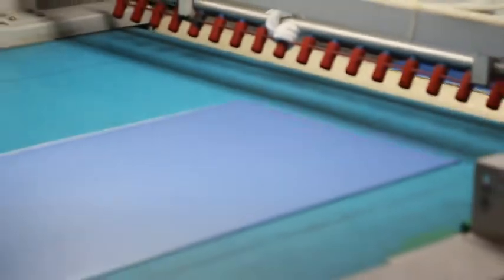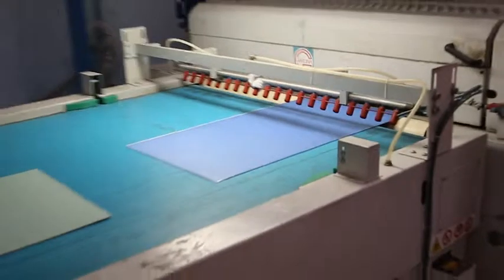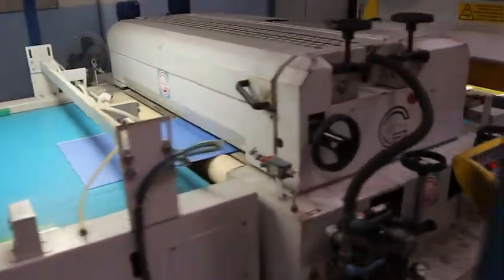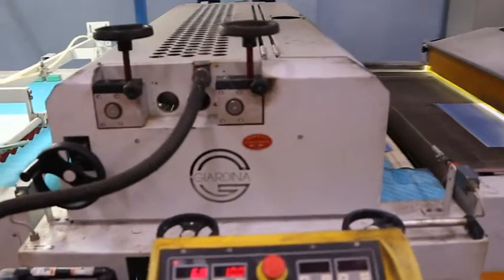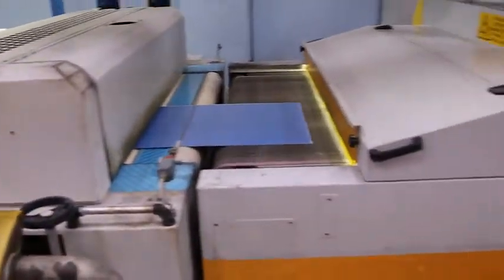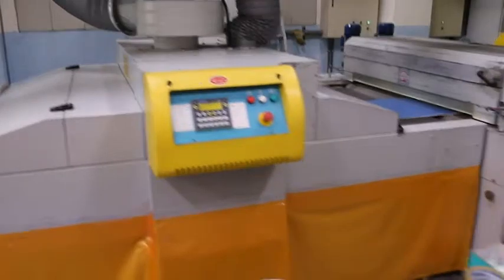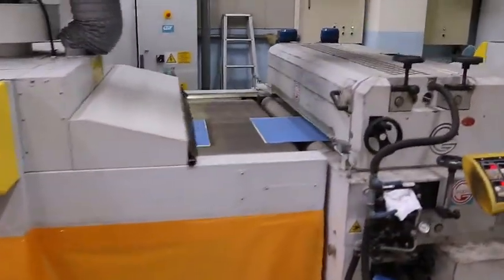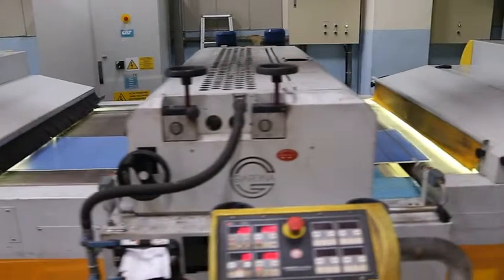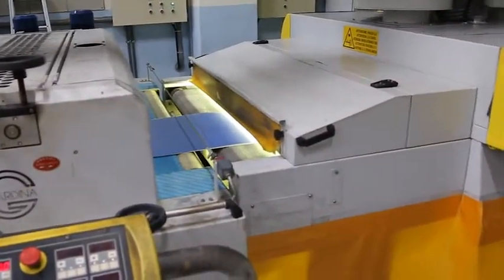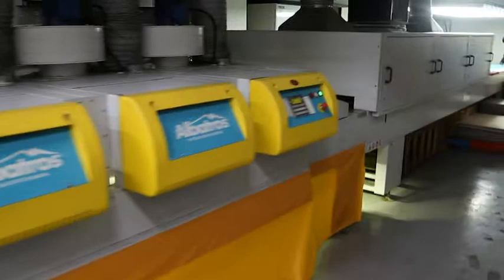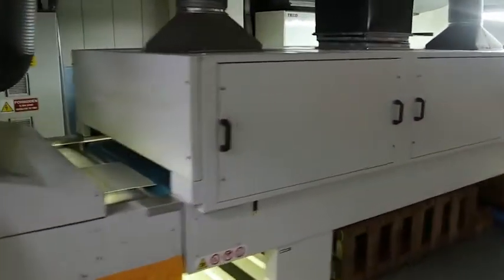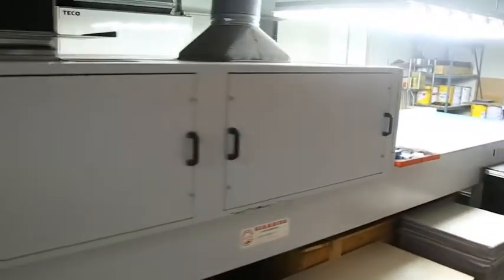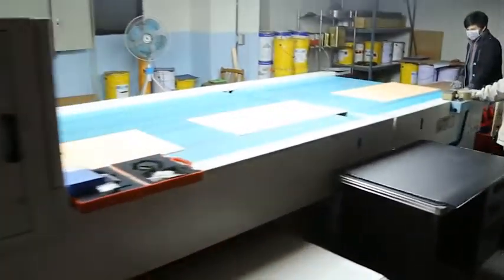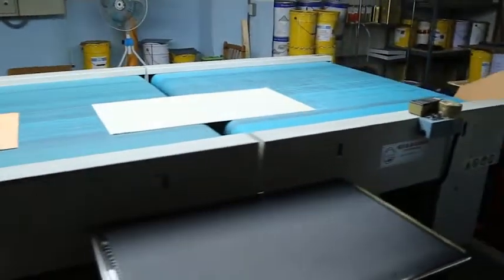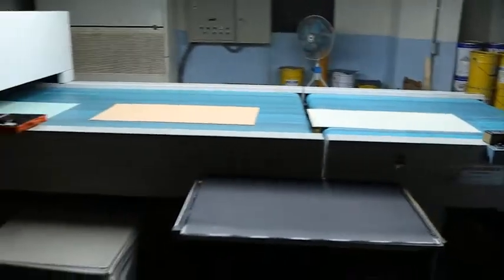We apply up to 3 times more polyurethane per square meter than most of our competition. How can we apply so much coating? With the latest in UV application and curing technology, cool lamps. These lamps bounce UV light off a special refractor lens and then onto the surface to be cured. This process keeps the slab cooler and allows the slab to stay longer under the 2-stage cool lamps. With a thicker coating, we can apply our glass bead slip-resistant polyurethane wear layer. Even under 10W30 motor oil testing, this coating excels at preventing slips and falls.